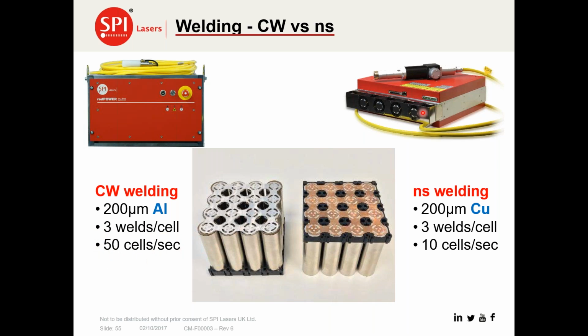With the nanosecond laser, here we're talking about 200 or 250 watt laser. We're looking at welding copper to the same cells. Again, 3 welds per cell, but we can achieve something about 10 cells per second or 30 welds per second. And again, it's all about horses for courses. We find that the nanosecond laser welds copper into other materials very well, whereas the CW welds aluminium into other materials a lot better. But, you know, at the end of the day, it is about average power that equals the productivity. And so in some instances, with the nanosecond welding process, to get the productivity, multiple laser sources are sometimes required.